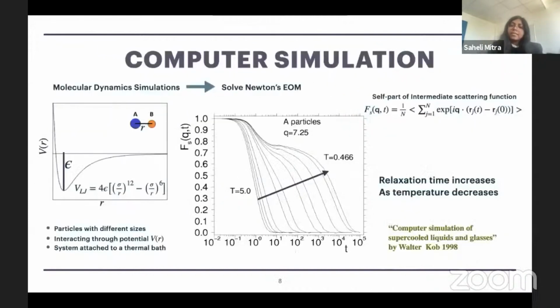Now, in the study of glasses, computer simulation has played a very important role. In this thesis also, we are using molecular dynamics simulation, where we start from particles with different sizes that helps us avoid crystallization, and we set up an interaction potential. For example, here I'm showing the Lennard-Jones potential, which historically has been used widely for the studies of glass forming materials. And once we have an interaction potential, we can solve Newton's equations of motion. And we can attach the system to a thermal bath to generate equilibrated liquid configurations at different temperatures.